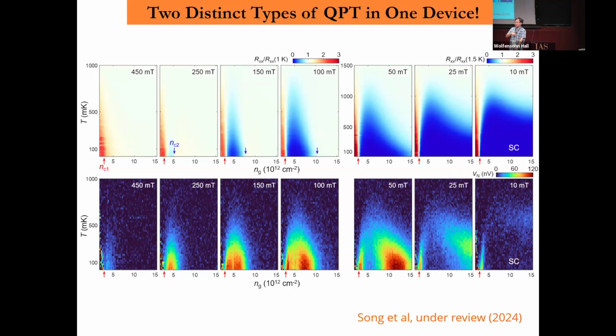This is the unconventional critical point that I was talking about. And then the other critical point moves dramatically with the magnetic field, like this. This one doesn't change. So there's something telling you these are two kinds, very different. Their response to fields is completely different. And then you measure the Nernst effect.